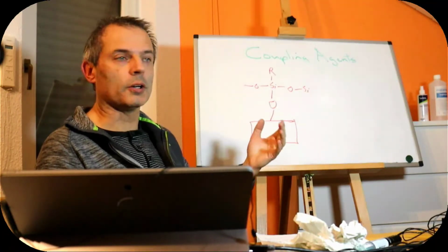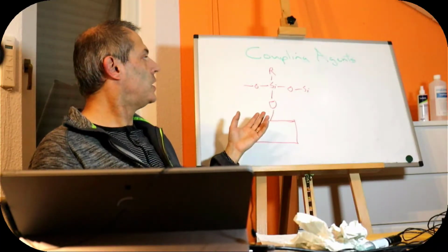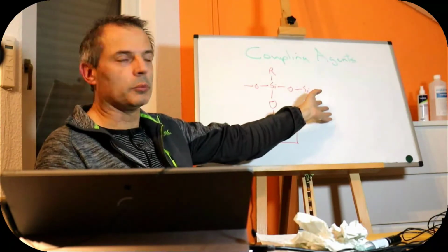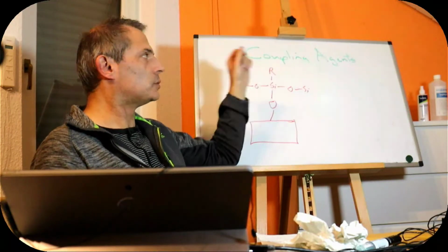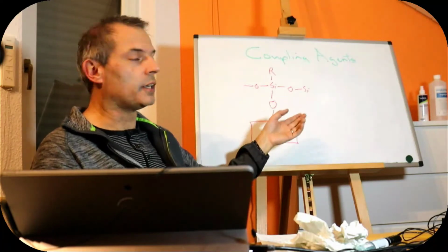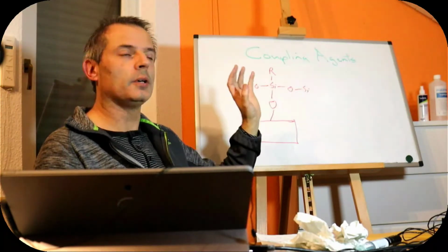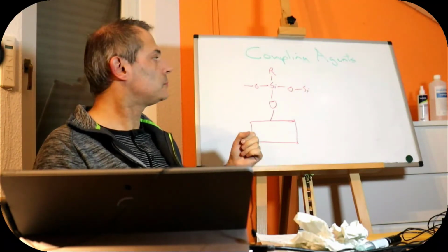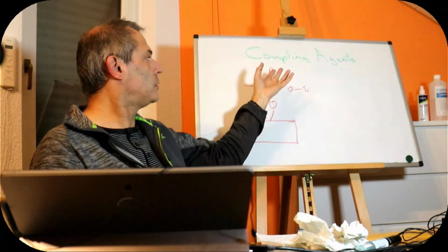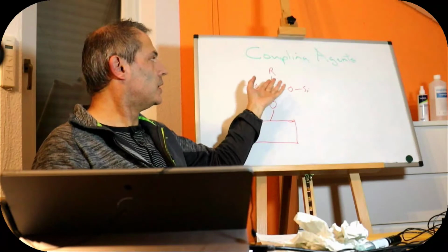This is often necessary on polymers that we've activated with a plasma or with a corona discharge, and then we need to have a coating on the top. We can start it going with this, and now we have our chosen group on the outside. For a metal, it's less important because metals tend to have metal oxides, hydroxides on the surface, and then we will have a lot of groups that we can attach to, although sometimes it's used on metals too. The important part is that we can choose what this reactive group or unreactive group is, and so we can determine the chemistry of our surface now to be what we want.